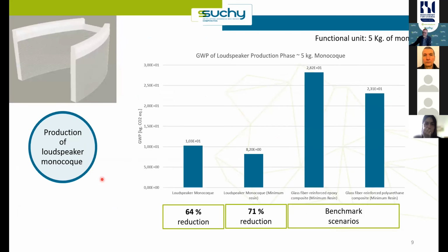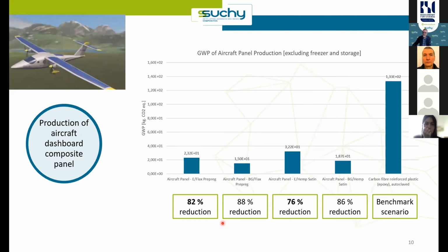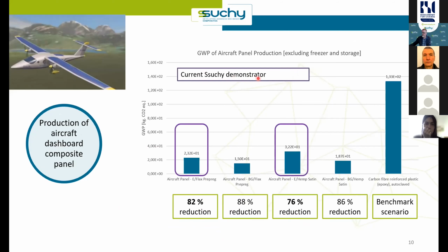reduction. For the loudspeakers, there we only have to look at the production phase. We could not include the benefit of the damping properties, for example. But also there we see that for these materials, we can indeed go to even higher reductions in global warming potential. And finally, for the aircraft dashboards, even for the production, we have further possibility to reduce global warming potential. For such demonstrators, it's 82% in case of epoxy flax and 76% in case of epoxy hemp. If we develop further and we use, for example, the bisglycol resin in the future, we can reduce even further.